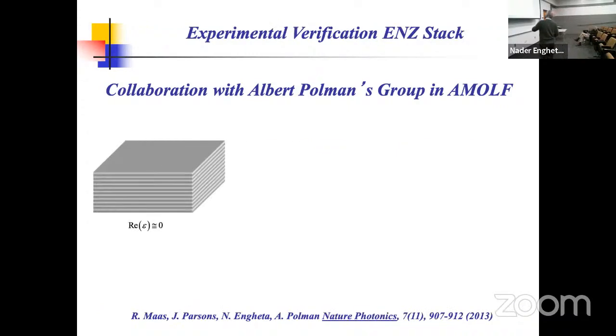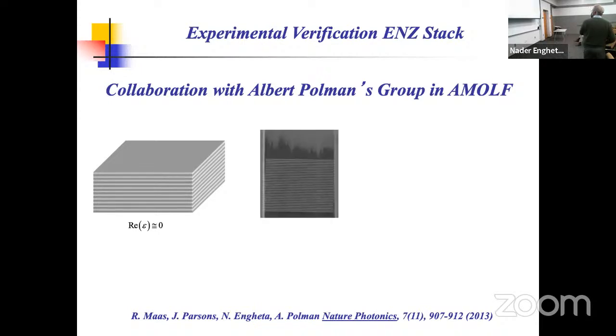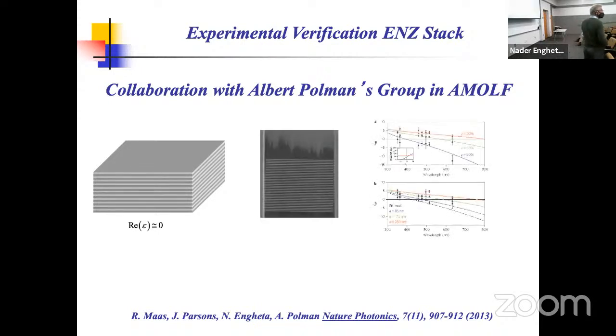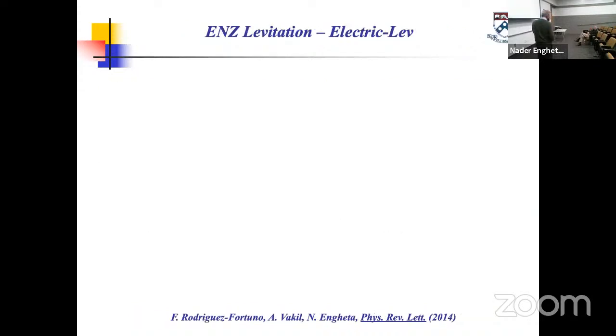Albert and I continued our collaboration, and we actually built a structure with a stack of silver and silicon nitride in order to create an ENZ structure. And with interferometry, we indeed showed that it actually has a zero crossing. Of course, this structure has more loss, but for some of the applications we want, it's not that relevant. Now, one of the other ideas we pursued is the following.